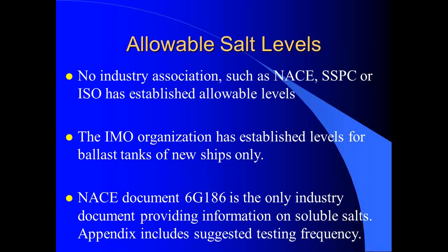6G186 has got a lot of information. It's the only industry document that tells you that abrasive blasting does not remove salts. I know a lot of specifiers who've had it in their heads for years that, well, all I have to do is abrasive blast it to white metal, and that removes all the salts. So if I've truly got a white metal, I've got a salt-free surface. Well, that's BS. It just doesn't work that way. Abrasive blasting may reduce the salts to some amount, but it doesn't remove them.